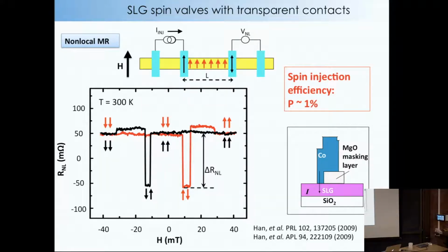Okay. The magnetic field doesn't affect the diffusion at all. The magnetic field could, in principle, affect the diffusion, but we haven't seen any effects of that. And even the presence of spin density, that should give you different diffusion coefficients for a spin up and spin down electron. We haven't seen that in our systems, but in gallium arsenide, now people are able to inject with such high polarization and density that these chemical potentials split so far that you start seeing signatures, and it's basically various new asymmetries that come out, like higher order effects, where the presence of spin is going to affect the flow of the following spin. So we don't see that because I don't think we're driving it hard enough to see it. But that type of effect you're mentioning, or related to what you're mentioning, has been seen in gallium arsenide recently.